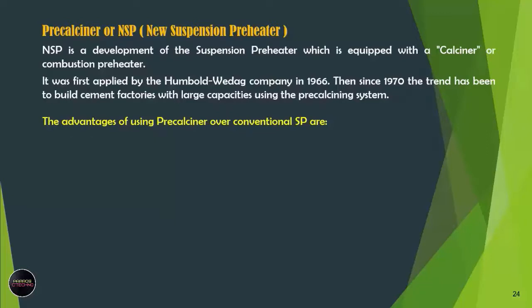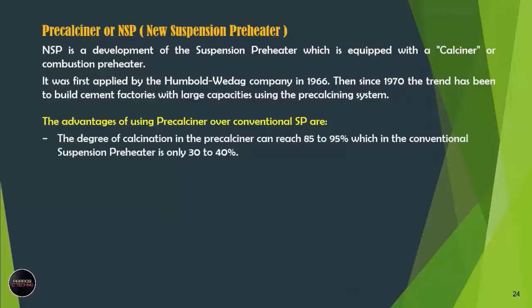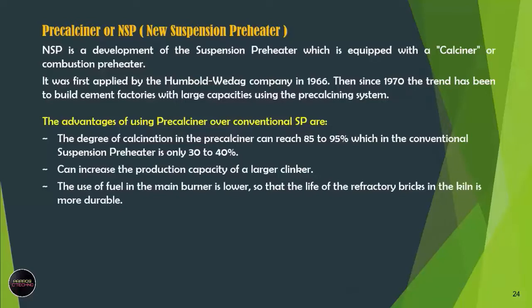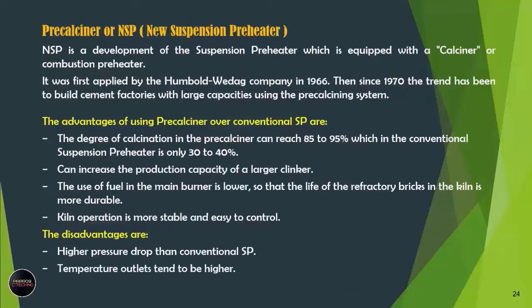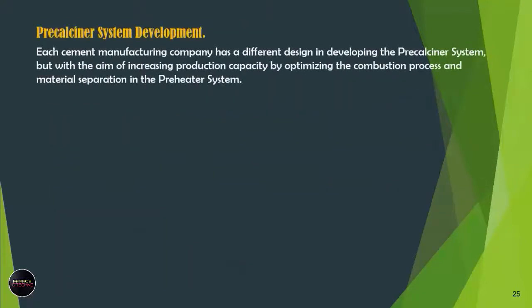The advantages of using a precalciner over a conventional SP are: 1. The degree of calcination in the precalciner can reach 85 to 95%, while in the conventional suspension preheater it is only 30 to 40%. 2. It can increase clinker production capacity. 3. The use of fuel in the main burner is lower, so the refractory bricks in the kiln are more durable. 4. Kiln operation is more stable and easy to control. The disadvantages are: 1. Higher pressure drop than conventional SP. 2. Outlet temperatures tend to be higher.